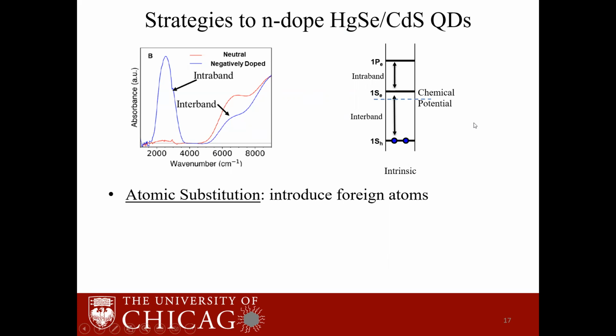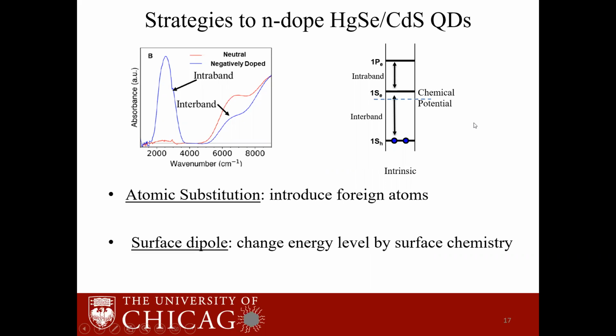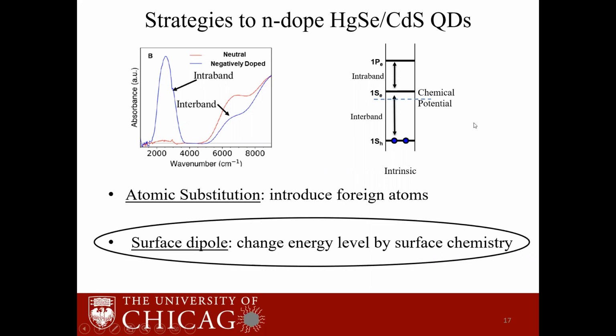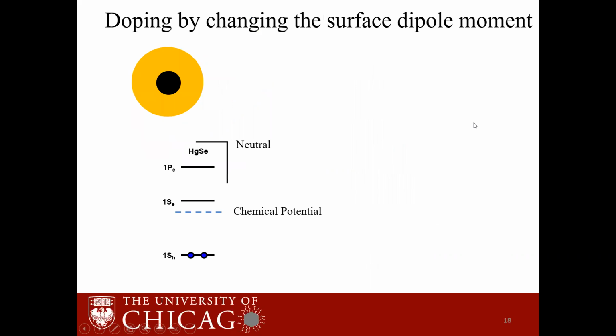Usually when we talk about doping, we think about putting foreign atoms into a material to introduce defect states. But another common way to dope quantum dots, which is much more convenient, is by changing the surface dipole moment. And this is the mechanism that we are using for doping our quantum dots. And in the next slide, I will go into the mechanism by which changing the surface dipole moment will dope the quantum dots. So here I have a cartoon of a quantum dot, and we have the valence band is full and the conduction band is empty. And we have the chemical potential is below the conduction band state.